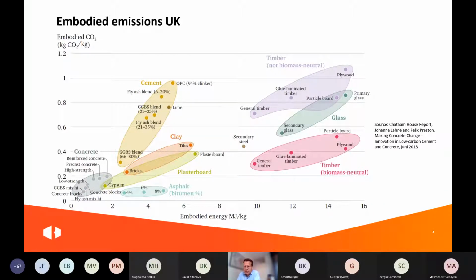And if you look at concrete, then it has actually quite a low CO2 profile compared to alternative materials, also compared to cross-laminated timber. Asphalt has a little bit lower CO2 profile than concrete, but of course, if you compare it on the lifespan of a concrete road of 40 years or more, then of course concrete is more environmentally friendly, not even taking the albedo effect and other aspects into account.